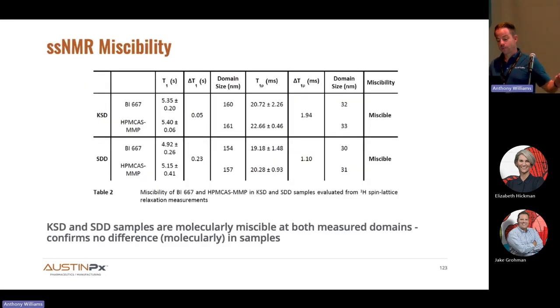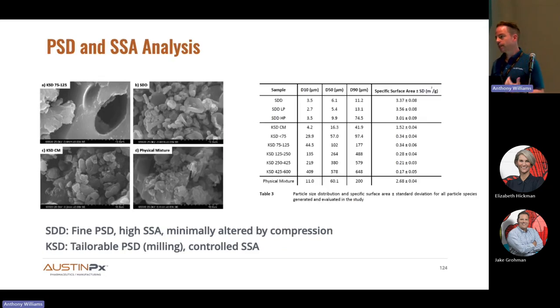And then when looking at miscibility, I know enough to say T1 and T1 rho, those parameters are similar, which means that in both cases, the drug and polymer are completely miscible, in this case to a domain size of about 32 nanometers. So based on the solid state NMR analysis, XRD, FTIR, at the molecular level, there appears to be no difference between spray drying and KinetiSol. At least per these analytical techniques, there doesn't appear to be a difference in how the drug is distributed in the matrix. But when we start to look at the particulate properties, you start to see divergence.